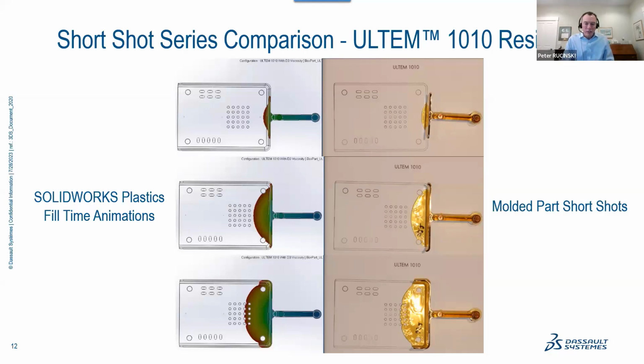Here we see the finished pictures. You might think, oh, it's very easy to create these short shots. Not so much. What's not quite as difficult is then matching up the filling patterns from the simulation predictions to the physical short shots. And so this is now what you see here. The reason why I like this so much is because there is essentially no denying what is happening on the right-hand side of the screen here. And as we look at these simulation predictions on the left-hand side, you can get a really good idea of how well the software is predicting the progression of the melt flow front as it flows through the cavity.